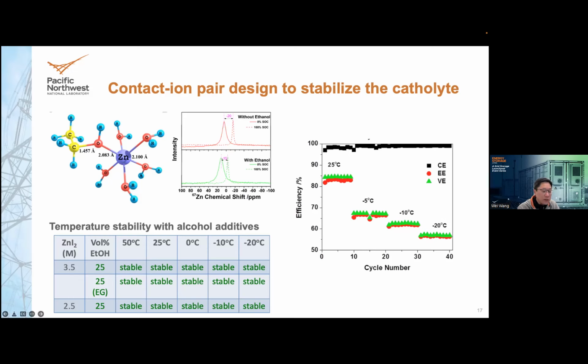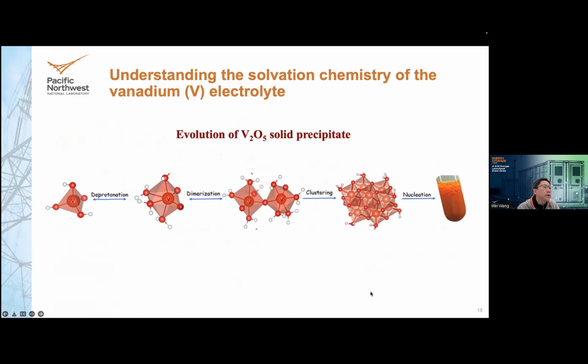Another one I want to introduce is adding an additive. If two active ions dimerize or polymerize easily, there is a way to add an additive to separate them out and prevent their polymerization, and that could stabilize the electrolyte as well. This was also done on the vanadium electrolyte. So this is what we understand about the whole vanadium 5 precipitation process.